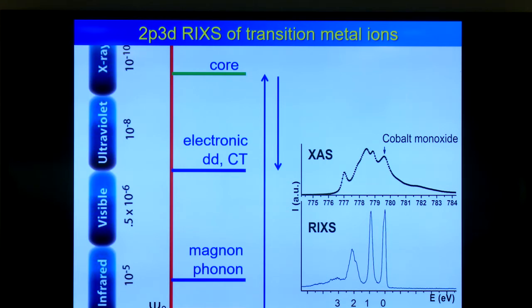So now I'm going to the second step, to use a core level to look at low energy excitations. So you go from your ground state to a core excited state, and then you go back to an electronic excitation, DD excitation or charge transfer, or you go to a magnon or phonon. So this is around 1 electron volt. This is around 10 millielectron volt, 10 to 100 millielectron volt, depending a little bit on the resolution of your beamline. So the beamline here will have 10 millielectron volt potentially. So then you can really study everything.